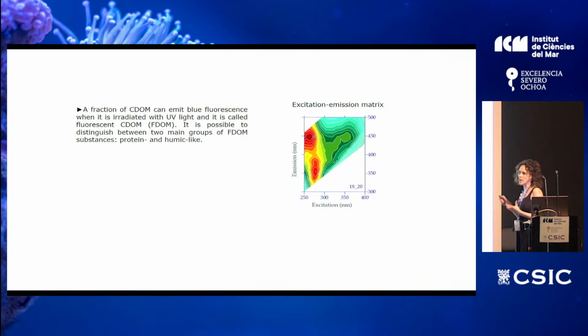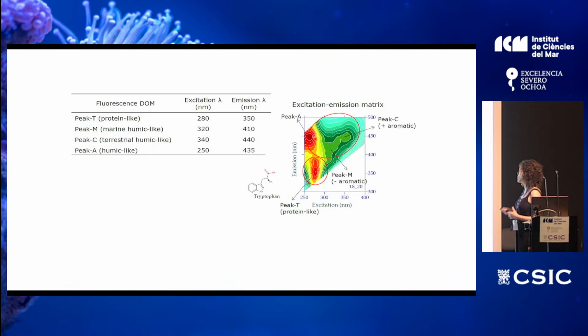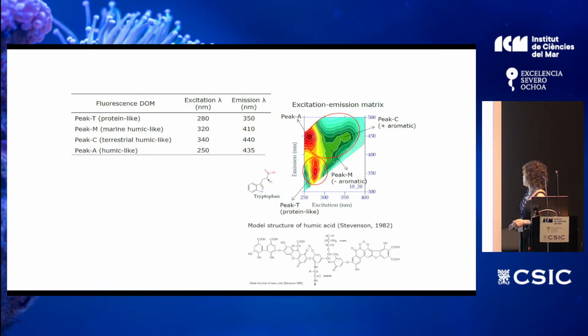This is just to show you how the natural DOM from the ocean looks. We have an area where the protein-like substances fluoresce. And this fluorescence is due mostly to tryptophan, but can also be due to tyrosine, which fluoresces at a bit shorter wavelengths. And then we have this area where the humic-like substances fluoresce. And usually we find these three peaks. Depending on the position of these peaks, we know whether the compounds are more or less aromatic, for example. We can also know the origin of the DOM from the fluorescence. And this is the structure, for example, of a typical amino acid and humic acid that would be giving fluorescence in this area, just to show you the structure.